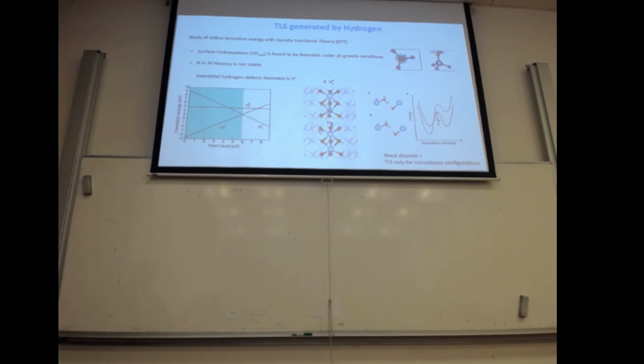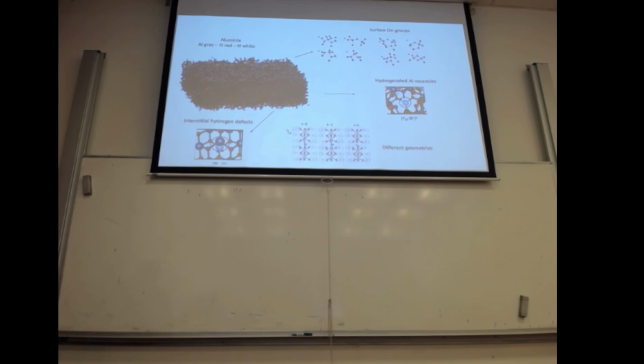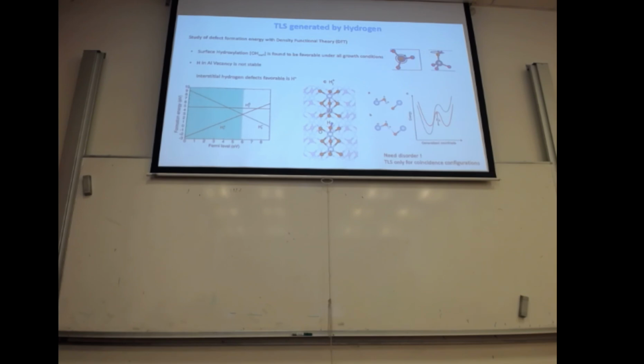So this is one feature. Now, as we saw in this picture, inside there are these hydrogens that occupy this. And I want to show you that these hydrogens are indeed responsible for this two-level system. There was a study about how this two-level system can be formed because of this hydrogen. As we saw, on the surface we have many OH. And what you see is that this OH forms a hydrogen-like two-level system like in SiO2, a sort of rotor. But there are also hydrogens that go into this aluminium vacancy. If you look at the formation energy, these are not stable, so they are more likely not important.